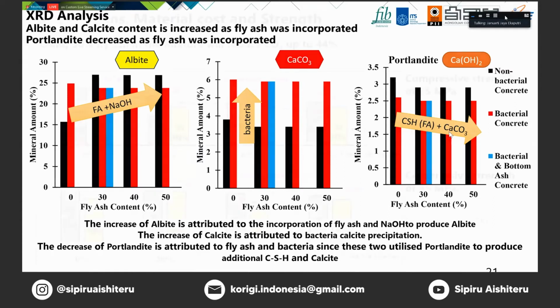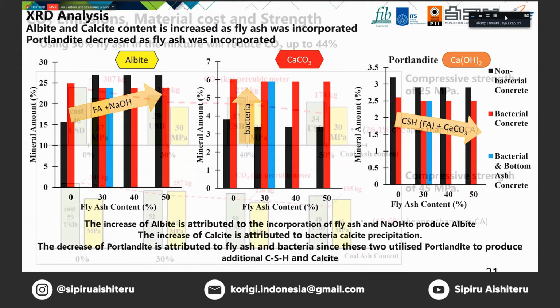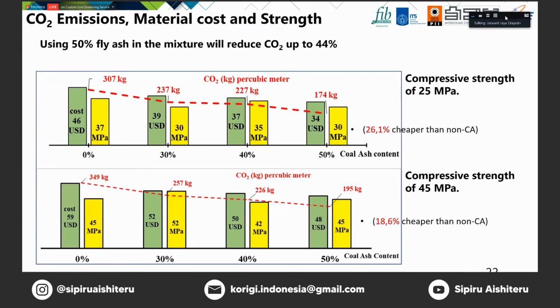And finally, we compare the result of normal strength and higher compressive strength. We found that there is a decrease of CO2 emissions by 44% for all specimens using 50% ash in the mixtures. And the cost of material is also reduced by 18 to 26%. And it is a very good contribution to the concrete ready mix industry to get the carbon credit actually.